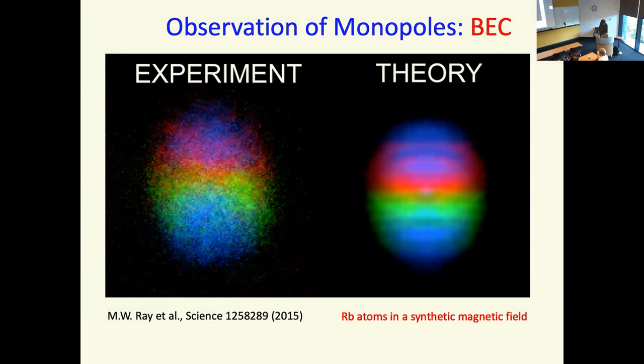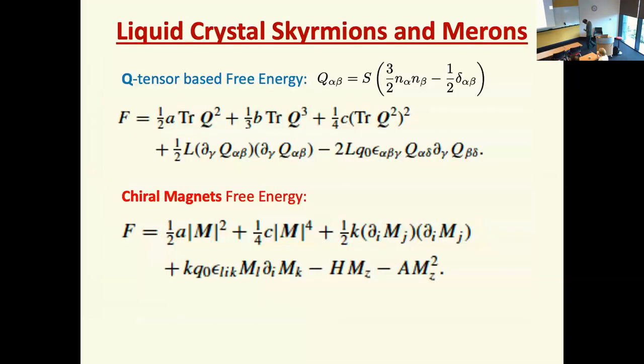Okay? Okay, I want to go back to liquid crystals for a while. All that I told you was something about magnetism. But do similar things happen in skyrmions, I mean, in liquid crystal skyrmion-like things? When you have liquid crystals, you have no arrows, unlike magnetic field or electric field. You have no arrows. Your directors, or molecules, are oriented. That's called n, the director. But if we want to do simulations or understand liquid crystals, sometimes there are disclinations and other singularities, and using the director field is not good. It leads to problems. So in the liquid crystal context, you use something called the Q tensor.